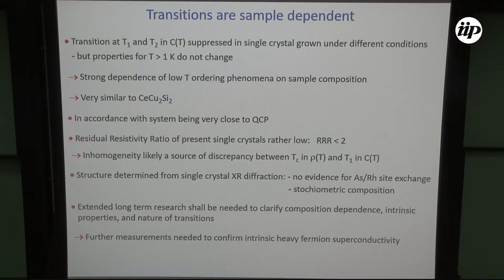So that seems to be very similar to CeCu2Si2, also in the way one can tune that. And that is in accordance with the system being close to a quantum critical point, because if you are close to a quantum critical point, you change the hybridization a little bit and you go from one side to the other side.